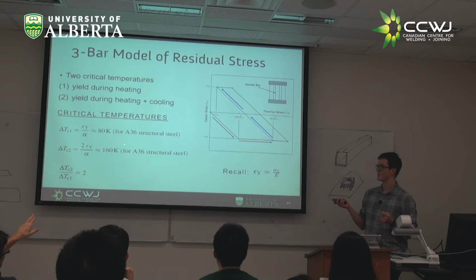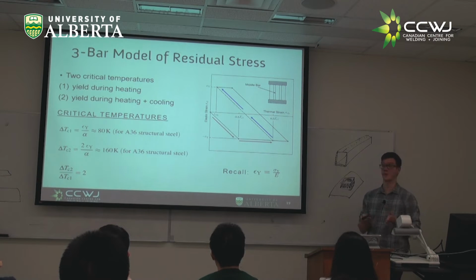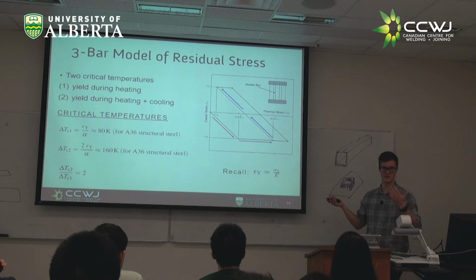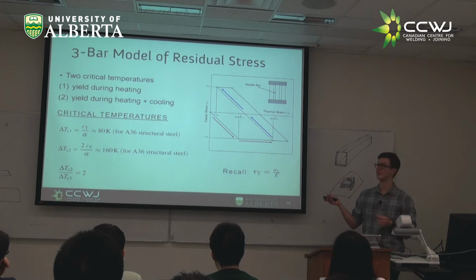So what you mean is 80 Kelvin is above room temperature? Yes, sorry. About 100 degrees C, not cryogenic, right? Sorry, yes, this is a delta T. So this is 80 degrees above whatever our reference temperature is. If this is a thermal strain, it is going to be a reference to our zero strain state, which in this case would be room temperature, give or take 20 degrees C. Now you can imagine if you start with a preheat temperature of 100 degrees C, then this becomes 180 Kelvin.